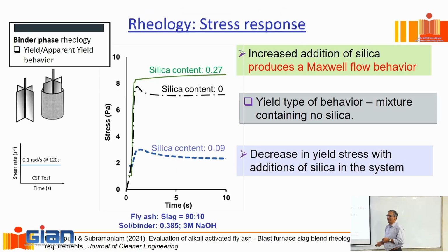The trough is playing a role. Okay, so when you start adding more and more silica, at some point you will shoot up here, and the viscosity of the solution increases, and that actually increases the stress, the resistance that I get. So that you see here in the resistance. But something more fundamentally different happens. Something fundamentally changes. Look at the shape of this curve. It actually goes up, reaches a peak, and then it starts flowing. Look at the shape of this curve. It's fundamentally different. What is different? It actually builds up to the peak and then becomes a constant.